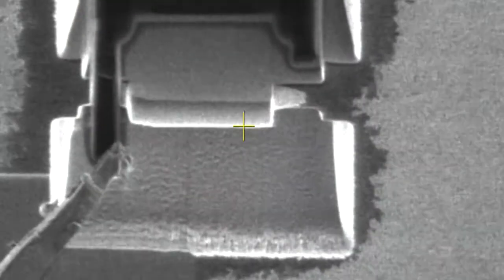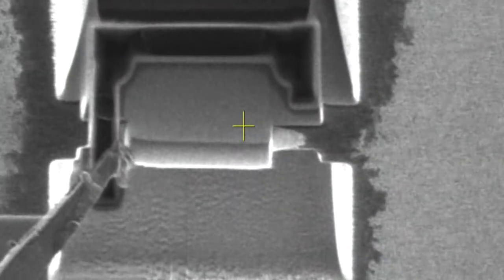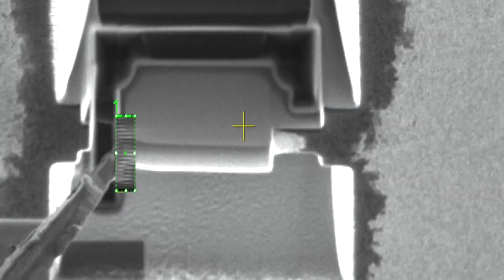The primary use of the FIB is to create samples for the TEM. In this case, a thin 2-micron window of the material is removed and placed onto a TEM grid, where it is then thinned to electron transparency.